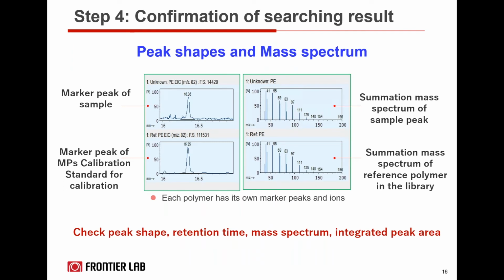Step 4 is an important step, which is the confirmation of the search result, where you use the software to, for example, I'm showing a PE polymer here. You can see the marker peak of your sample and non-sample, and you can compare it to the marker peak of your microplastic calibration standard used for the calibration.